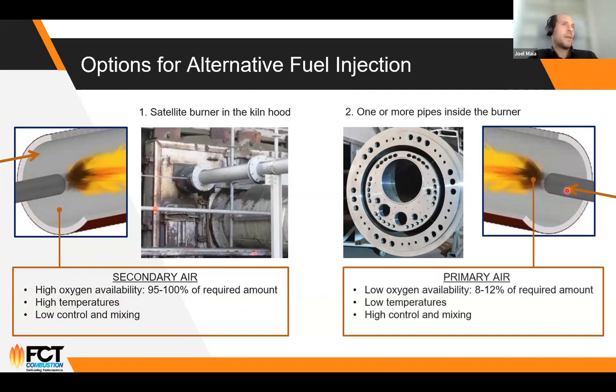Again, there are some benefits on this solution, and the main characteristic is that through the burner, you're injecting just a small amount of the air required for the combustion. We are talking about 8–12%, depending on the type of kiln, a bit more, a bit less. At this zone, especially closer to the burner, you have lower temperatures. However, the main advantage is that you have a very high control and a very intense mixing of the alternative fuel with the remaining air around.